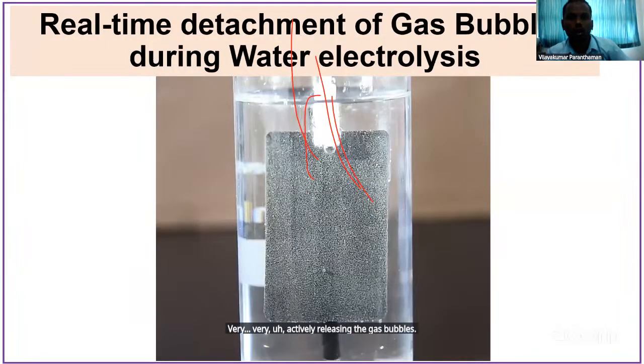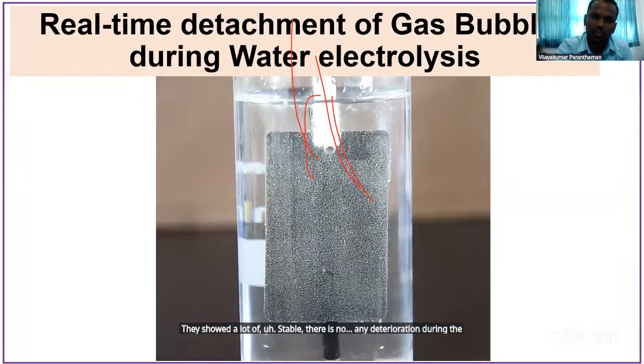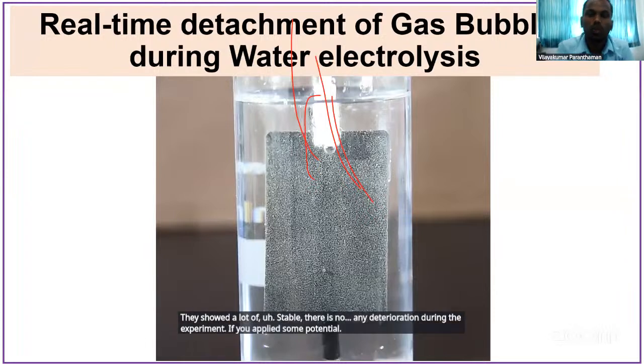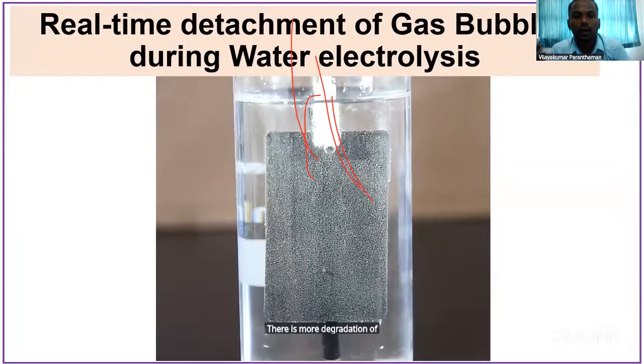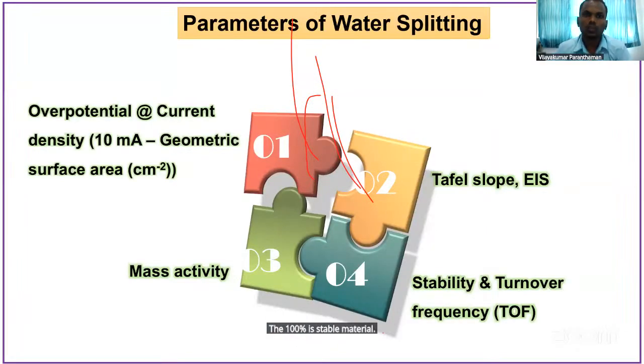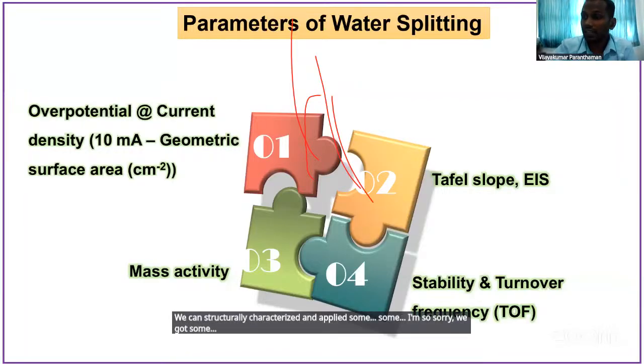They show a lot of stability. There is no deterioration during the experiment. If you apply some potential, there is no degradation of the electrodes. So we decided our material is a 100% stable material. So once we synthesized, structurally characterized and applied it, we got some active results.